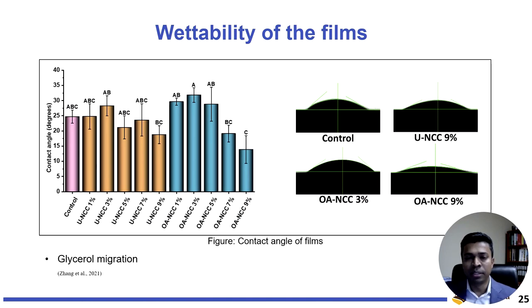So then we did some research to find out why we are not seeing improved surface hydrophobicity, which it should generate with the hydrophobic groups we are adding into the packaging film. What we realized is that when we add the hydrophobically modified nanocellulose into this packaging material, the migration of glycerol, the plasticizer we used in both studies, from the packaging film over time onto the surface is much higher compared to the previous modification. Because glycerol is hydrophilic, it reduces the contact angle, which is not something we expected. But right now we are doing research on how to mitigate this issue and improve the surface hydrophobicity using the same modification for nanocellulose, while trying to reduce the glycerol migration.